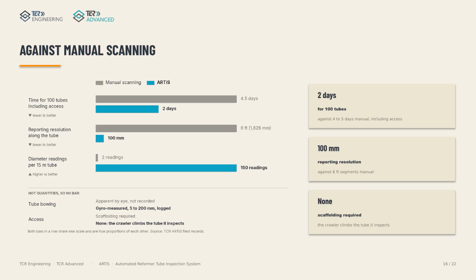The commercial case is straightforward. 100 tubes take 4 to 5 days by manual scanning once scaffolding is included. ARTiS does the same 100 tubes in 2 days with no scaffolding at all. Manual results are reported in 6-foot segments, which averages away a local hot band. ARTiS reports at 100 mm resolution.